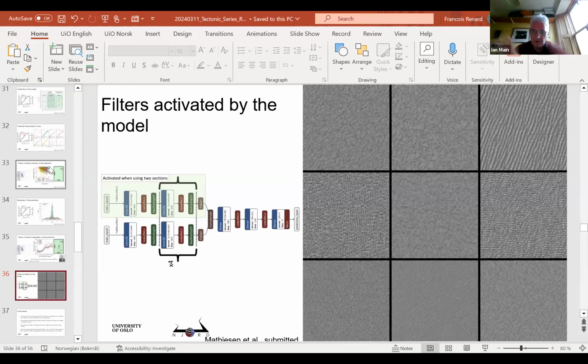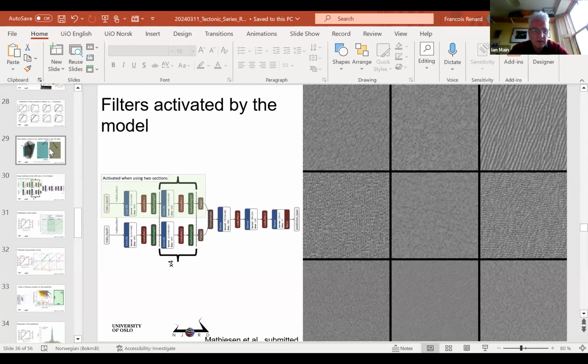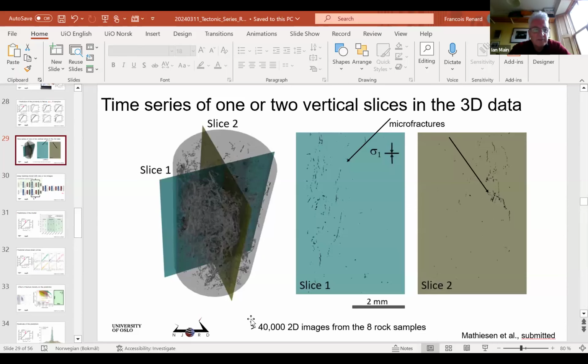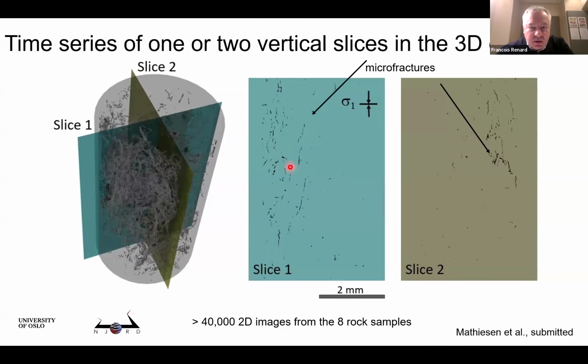And that happens before the time it fails. Like it's part of the process of finding the optimum in some free energy function or whatever to break the rock. But that's perhaps what the model is seeing. If you look at this, you see this one is perhaps a series of mode 1 cracks that have aligned. And in the image now you start to see this angle around 20 degrees appear. And that's probably a signal that this linkage process has occurred to create this 20 degrees direction, and that the sample is closer to failure.